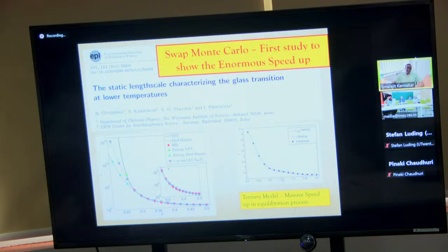And I'm saying the estimated time scale because this is the place where you do not have an idea about what the relaxation time could be. If you fit your high temperature data up to this area via various forms, the lower estimate turns out to be at least 10 to the 10, which is at least a few fold speed up in the dynamics.